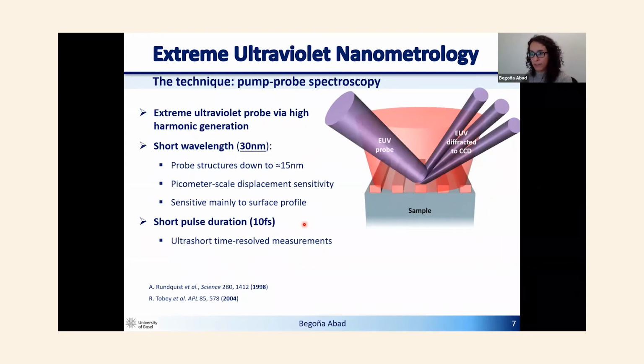Okay, so we launch our dynamics, but we need to probe them. And here's where we use the extreme ultraviolet light. We use this light generated by high harmonic generation. And in our case, we use a 30 nanometer wavelength. This allows us to probe structures down to 15 nanometers, which is well below the diffraction limit of visible light, and we can probe picometer scale displacement of our nanolines. Moreover, this is sensitive mainly to the surface profile. And as I said before, due to the short duration of the pulse, we can do ultrashort time-resolved measurements.